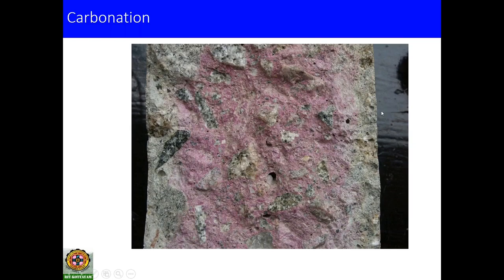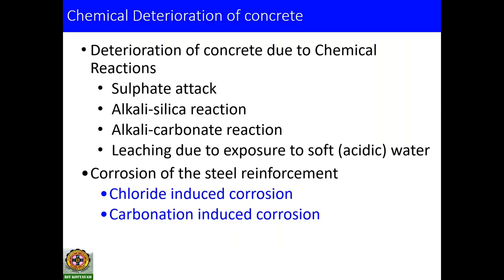So that means from here to this level, the carbon dioxide had penetrated, and this carbon dioxide had reacted with the calcium hydroxide, forming calcium carbonate. Because of the consumption of the calcium hydroxide, the alkalinity is lost, and that is why you see a colorless portion here. Here the calcium hydroxide is still remaining, and you can see a pink color. So I just want to show you some pictures of that.